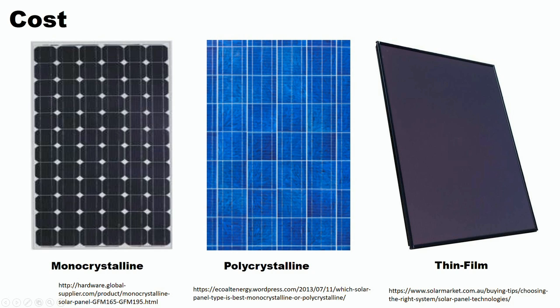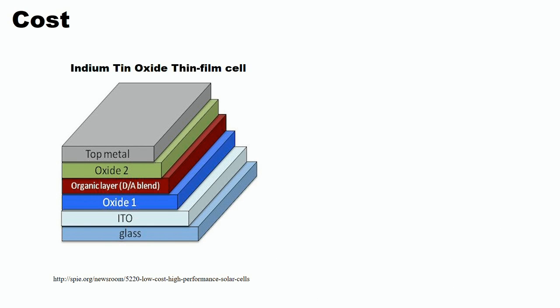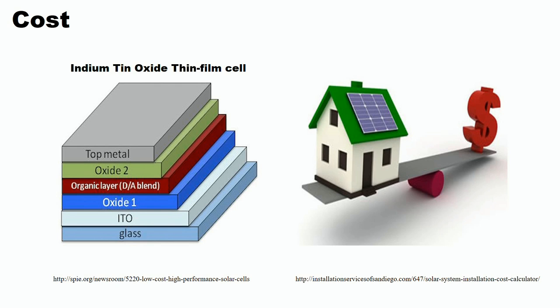Thin film solar cells are relatively cheap because they are made of a polymer material that is coated in a photovoltaic substance, but they can become costly depending on the type of photovoltaic material that is used. For example, indium tin oxide, or ITO, is a very good conductor used in organic solar cells, but it costs almost $200 for only 5 grams.